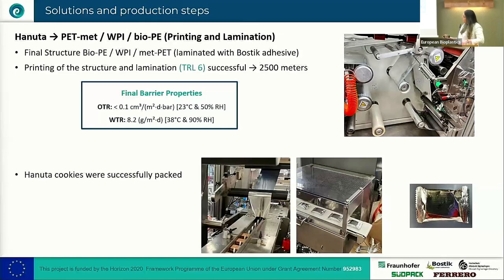Again, depending on the substrate, we have better results. Here, we work for a flow pack, and then we laminate successfully PET metallized with whey protein coating and bio-based PE. The printing and lamination trials were really good, and we produced successfully 2,500 meters of this material. The final barrier properties are also very good, as you can see here, and we managed to pack the cookies on this packaging.